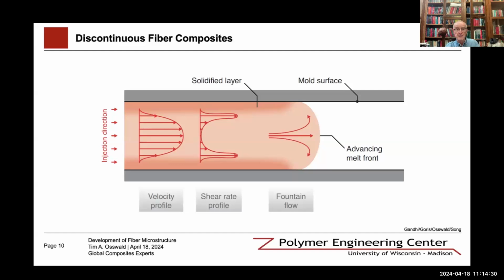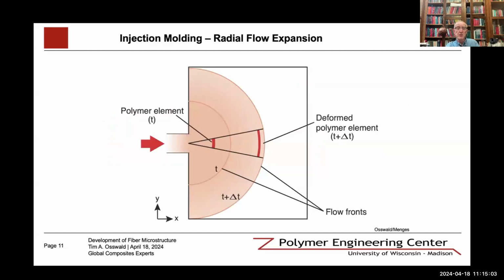So there are different things that cause orientation. One of them, of course, is the advancing melt front, so that you can see a fountain flow effect that leads to an orientation, a stretching in that area in the direction of flow, which lays fibers on the upper and lower surface of a molded part in the direction of flow. So it creates a skin layer in the part where you have a preferential orientation in that direction.